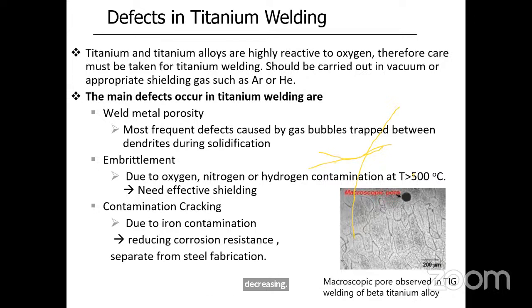So the main defects in titanium alloys are mainly weld metal porosity, which you will get if you don't choose proper shielding. Then these gases may enter between the dendrites, and it's difficult for them to escape. That's why this porosity will form. Embrittlement mainly occurs because of hydrogen, nitrogen or oxygen contamination. Contamination is the main problem.